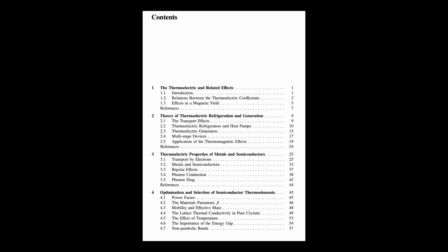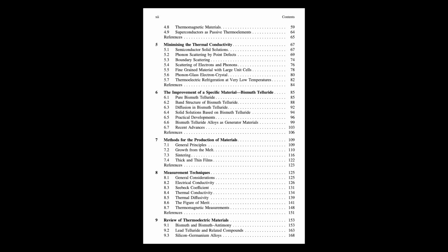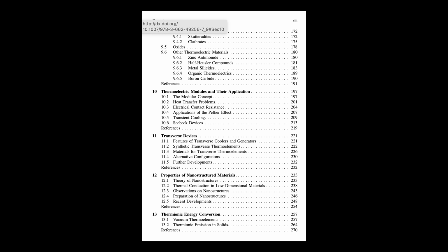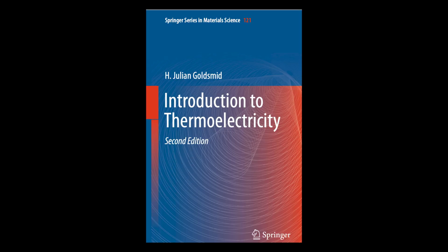Okay. The outline then loops back to thermomagnetics, Ettingshausen and Nernst coefficients expressed using Hall mobilities. How does that help? The Hall mobility characterizes carrier movement when you have both E and B fields. It's related to drift mobility but can differ, especially with mixed conduction. It turns out you can mathematically express the Ettingshausen and Nernst coefficients using these Hall mobilities, carrier concentrations, and things called Hall factors. These links help us understand and maybe predict how magnetic fields can manipulate heat and charge flow, crucial for designing thermomagnetic devices.